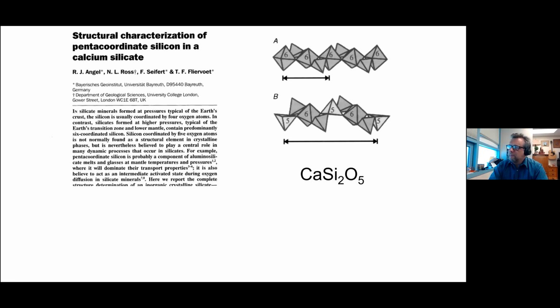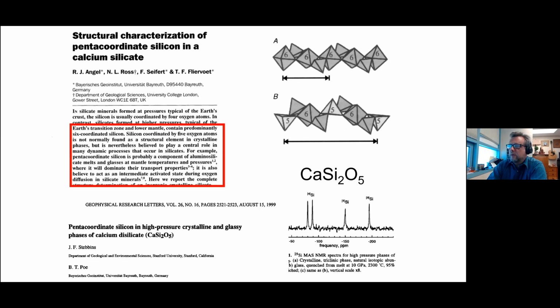It's a rare silicate material that doesn't occur in rocks at significant quantities, but it has this unusual property of having one of the silicon atoms in a 5 coordinated site. So we have not 4, not 6, but 5 oxygens coordinating this one silicon. The studies of this particular phase were done both with X-rays and with NMR spectroscopy, where Jonathan Stebbins did a lot of very nice work about 20 or so years ago.